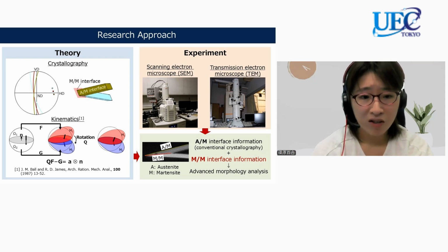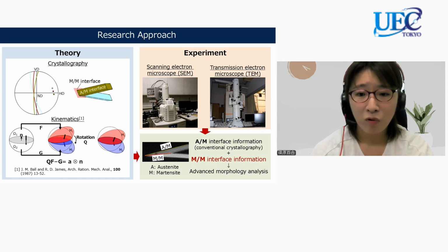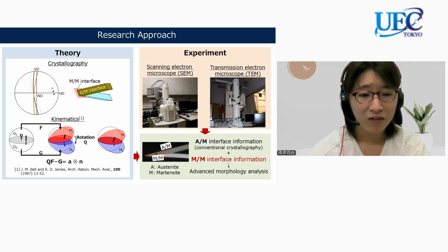We solve this problem using kinematics in addition to crystallography. The validity of the theory is tested using an electron microscope, which is a powerful tool for observing morphology and obtaining crystallographic information. By combining theoretical analysis with experiments, we can obtain information on the martensite-martensite interface. This information allows us to perform advanced analysis of martensitic microstructures.